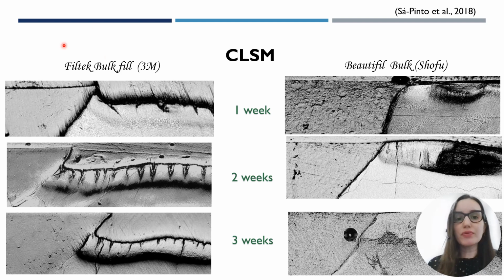And we confirmed those results using CLSM device. So loss of enamel only for Filtek Bulk Fill group. And moreover, we observed a bright zone for the Beautifil group near the composite restoration.